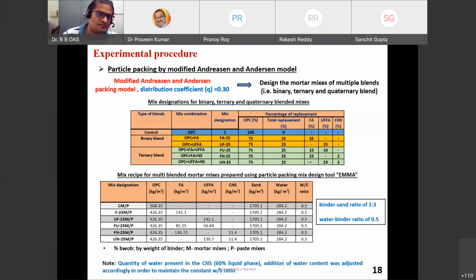For example, if you go to OPC, fly ash, nano silica, this 25% is divided into 23% of fly ash and 2% of nano silica. So we have OPC plus fly ash, which is 75-25, and OPC plus fly ash plus nano silica, that is 75, 23 and 2. That is the distribution. Here M designates mortar and P designates paste. Because we went for some advanced characterization studies, which I'm going to talk about today, there we did it with the paste.